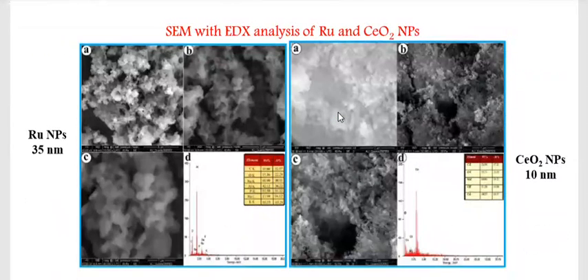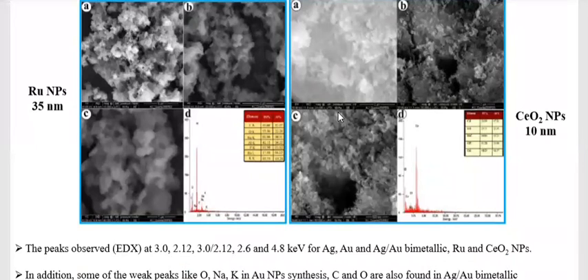EDAX is elemental analysis. The gold nanoparticles and the gold-silver bimetallic nanoparticles show spherical morphology in the range of 20 to 50 nanometers, and the bimetallic shows 10 nanometers, confirmed by the EDAX profiles. Another thing is that the ruthenium nanoparticles show 35 nanometer spherical nanoparticles, and the cerium oxide nanoparticles show 10 nanometers. When you get below 5 nanometers, it is considered quantum confinement.